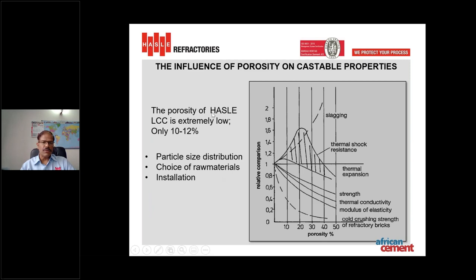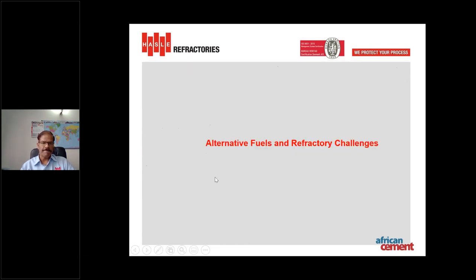HASLE always tries to keep the open porosity of the castable at a minimal level. We are able to achieve 10 to 12% open porosity, which is achieved by our unique particle size distribution, choice of raw materials, and a proper installation procedure on site. So now coming to the type of alternative fuels and refractory challenges.